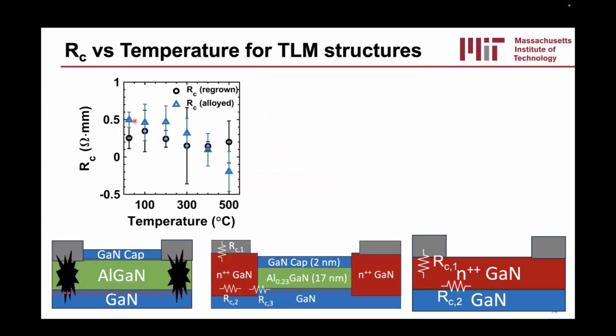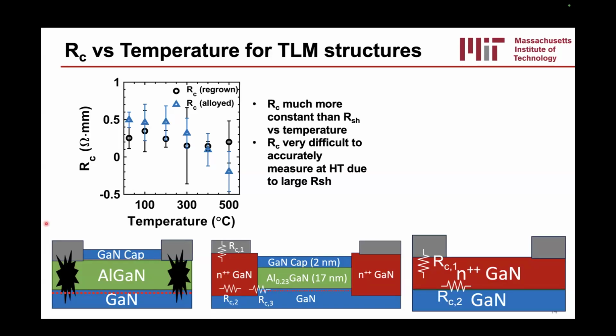Okay. And more importantly, from that linear fit, we can actually extract the contact resistance as a function of temperature for both the regrown structures as well as the alloy structures. And we can see that in general, there's not a whole lot of change over the full temperature range, definitely not that 10x we see in the sheet resistance. And for the most part, the error bars get really large as we increase the temperature, mostly because the sheet resistance gets very high, and so it becomes difficult to extract that y-intercept.